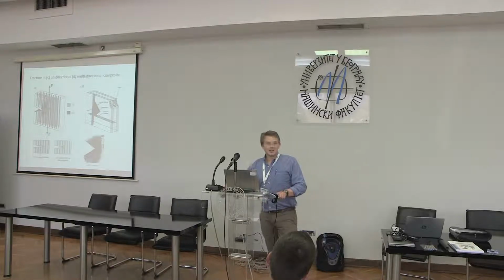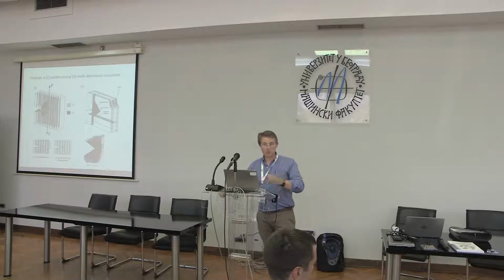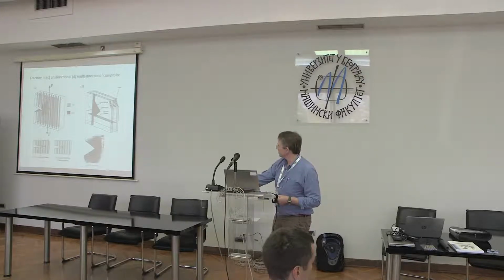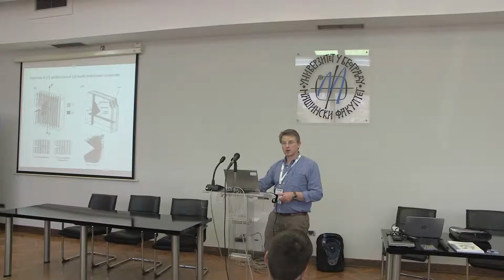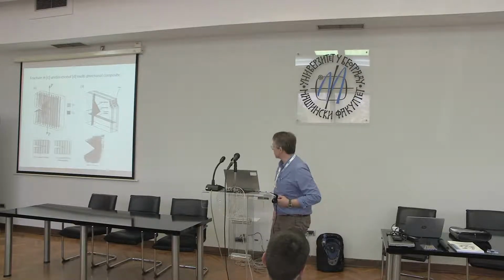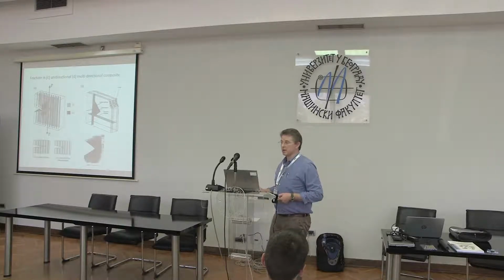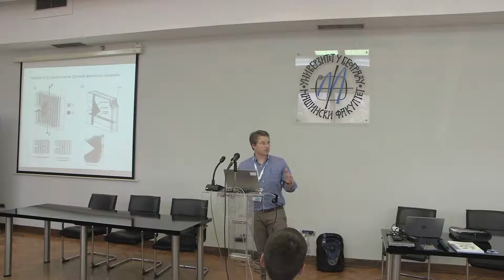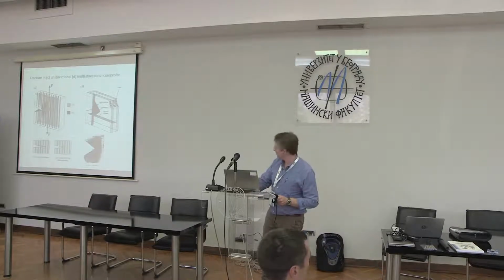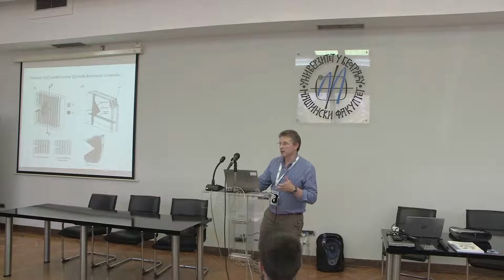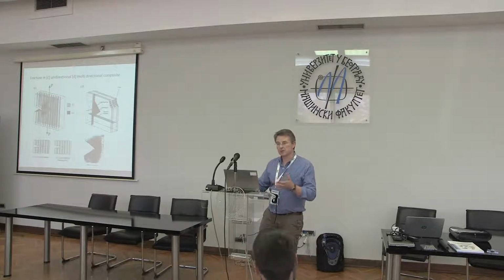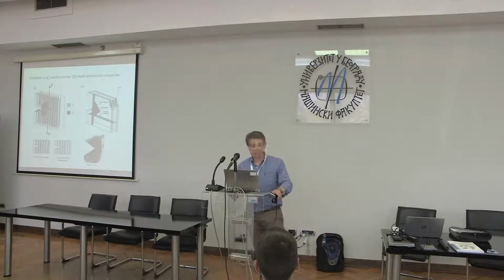Relatively complex geometries are required to force transverse fracture across the fiber layer. So what will tend to happen is the crack will tend to run in between the fibers, and we'll get what we describe as a lateral splitting, which we determine as delamination. So when we talk about composite materials, what we're very interested in is indeed what's actually happening between the layers of fibers, and this weak interlaminar layer where we're actually getting cracks propagating at relatively low amounts of applied energy. So in terms of the composite fracture mechanics, we're very interested in what's happening between the fibers, and in polymer fracture mechanics, obviously we're interested in what's happening in the plastic zone and or a damage zone.